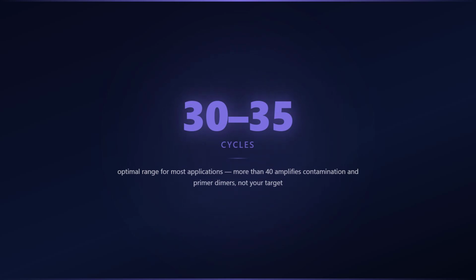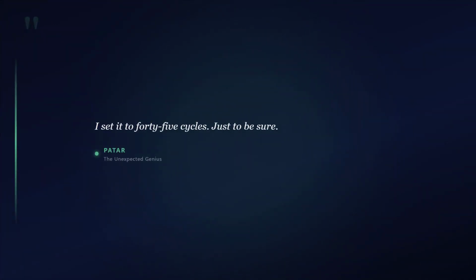If you need more than 40 cycles to see a product, your template quality is the problem, not the cycle count. I set it to 45 cycles, just to be sure. 45 cycles means you're amplifying noise. If your band is real, you'll see it at 32. If you need 45, the band is not real. It's a contaminant or a primer-dimer. You've just made a lot of something you don't want.